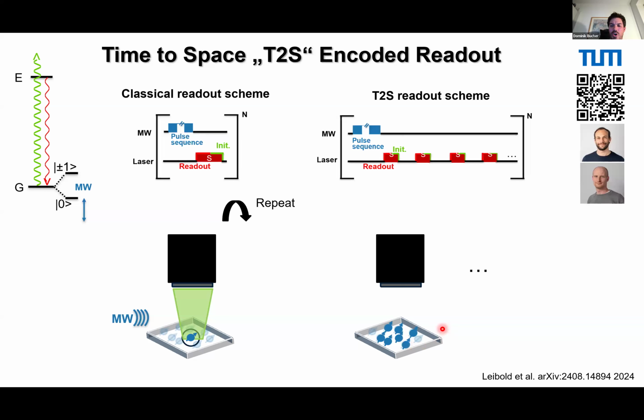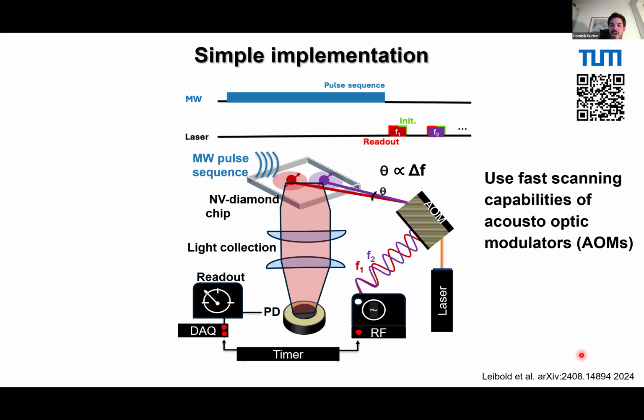So what we do is, we manipulate all with the microwave, and then basically we scan, read out here the quantum state, here, here, here. And of course, this has to happen much, much faster, or very fast, in order to not lose time while you scan your laser spot. And you may say, oh, that's a very complicated thing. How would I do that? And the nice thing is basically all pulsed NV experiments can do that, because we can use just our AOM, our acousto-optical modulator, which is built into an experiment. So we use typically the AOM for turning on or pulsing our laser.